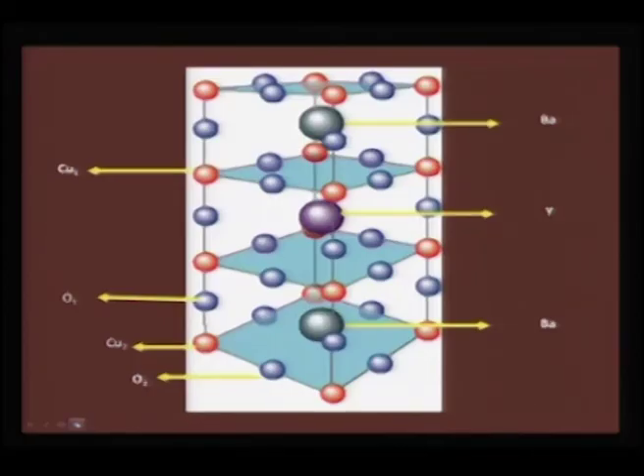So, the issue of oxygen content actually brings us back into focus what sort of a unit cell that we have, and if we take a close look at it, we see that the barium ions are placed here, and the yttrium ion is actually separating these two perovskite unit cells, and then you would see copper in this chain and also copper along the C axis.